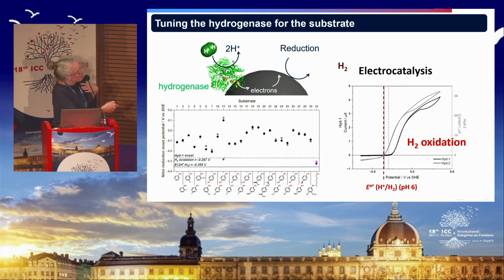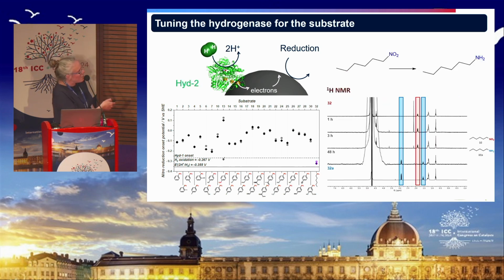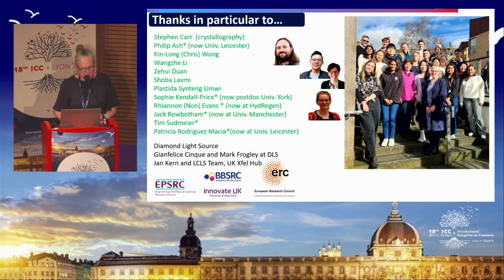But when we want to look at aliphatic nitro compounds, like nitrohexane here, we need to turn to hydrogenase 2 from E. coli, which is not quite so robust, but does work right at that thermodynamic potential as a reversible catalyst. And so we hypothesized that it should be possible to put HYD2 in place of HYD1 on this system and be able to extend this to aliphatic nitro compounds. And indeed, here are some NMR spectra showing that we are successfully hydrogenating the nitrohexane using HYD2 on carbon catalyst. So it's a nice example of how the electrochemistry of the enzymes allows you to design a catalyst and tune what you're doing. So with that, I'm going to thank all of the people who've been involved in this work.